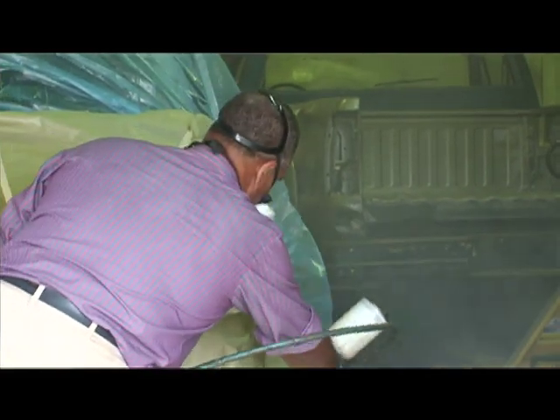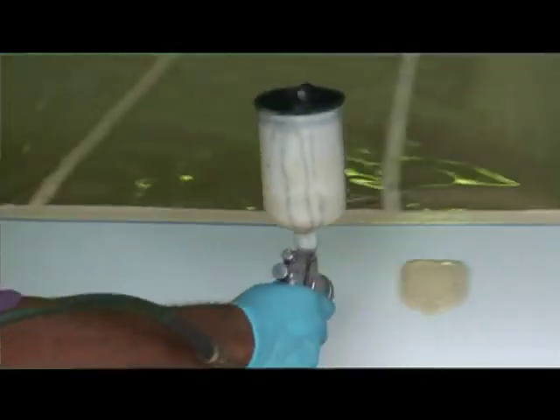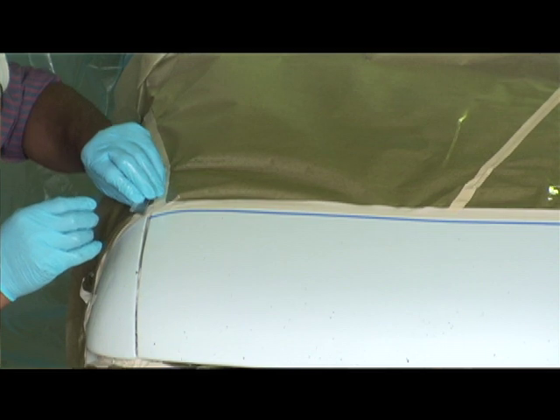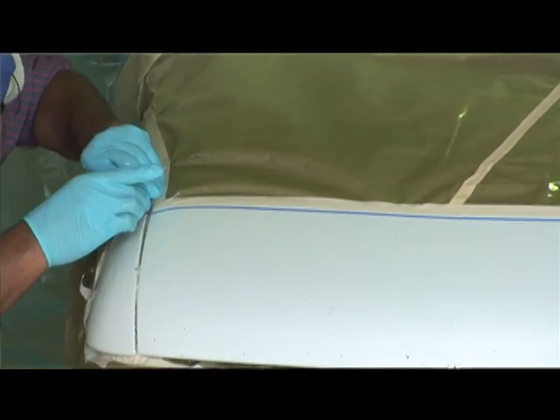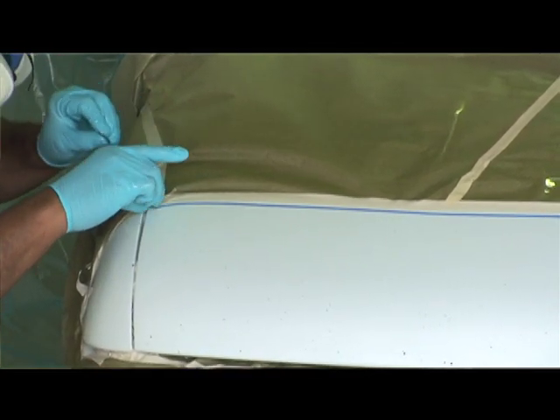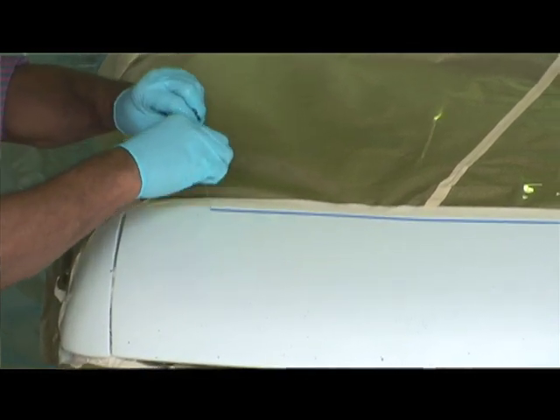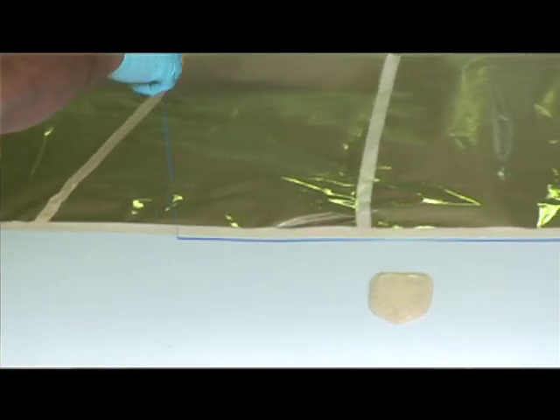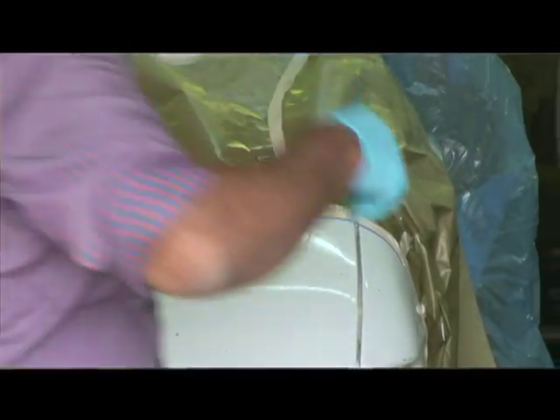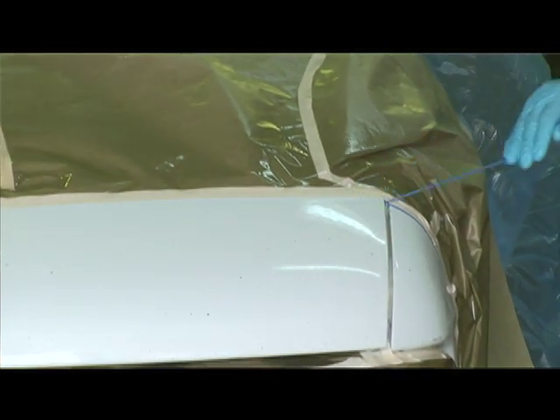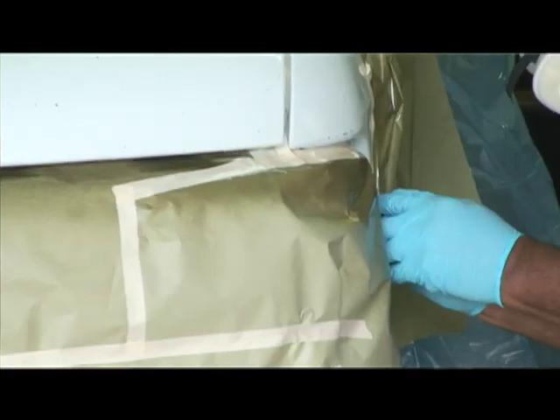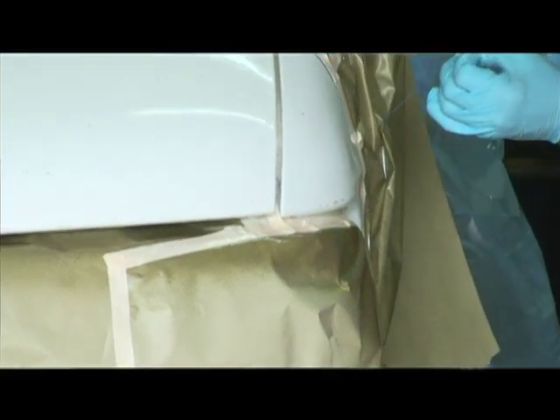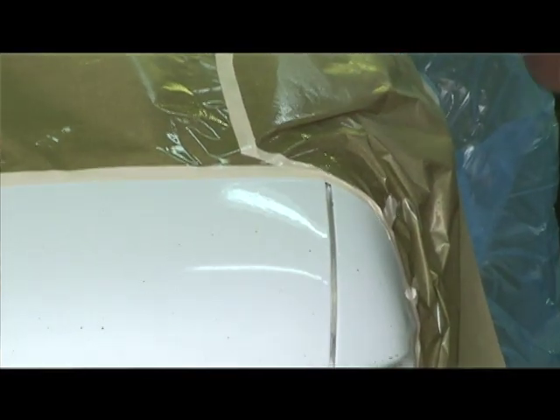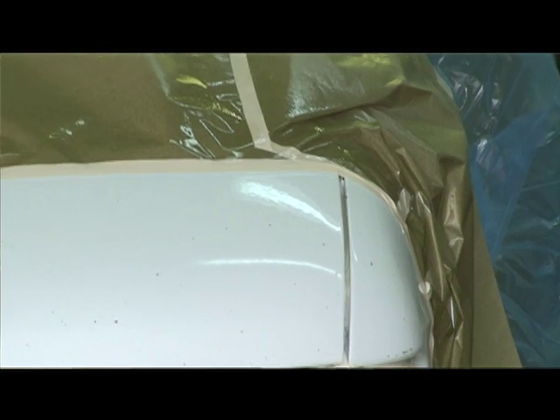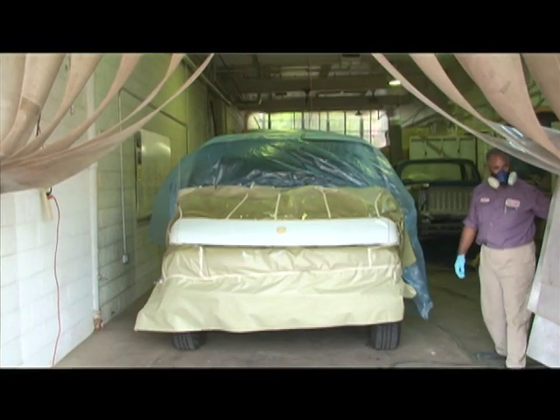Spray even coats at 2 wet mils per pass, being sure not to exceed 4 mils total film thickness per coat. If you exceed about 4 mils per coat, the acrylic urethane reducer will not be able to volatilize through the coating film fast enough before the gelling of the film locks the solvents into the film. This will result in an off-color coating. If you spray the material in even coating thicknesses at low mil thicknesses per coat, and with an even pace, you will get a Class A type finish and will not need to perform step number 4 as described earlier at all.